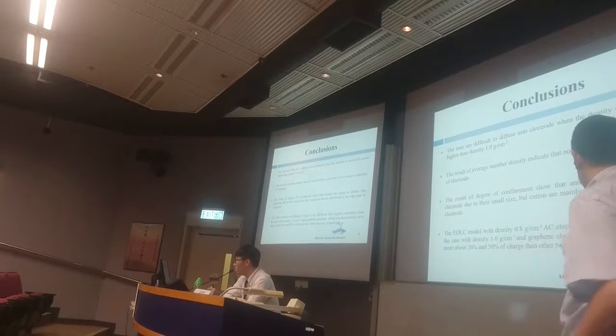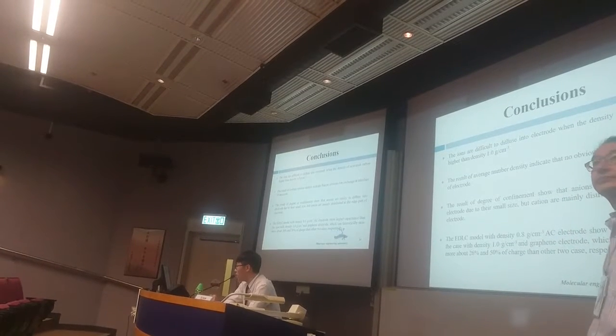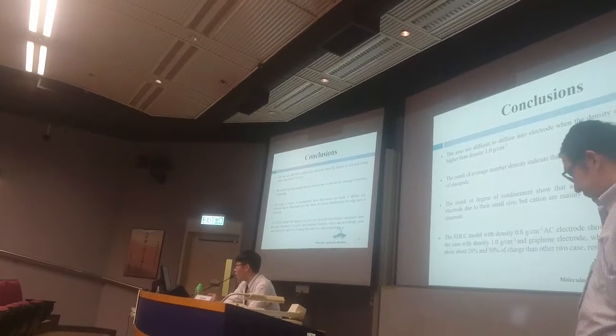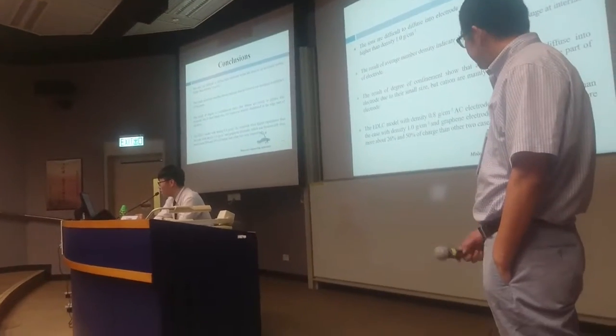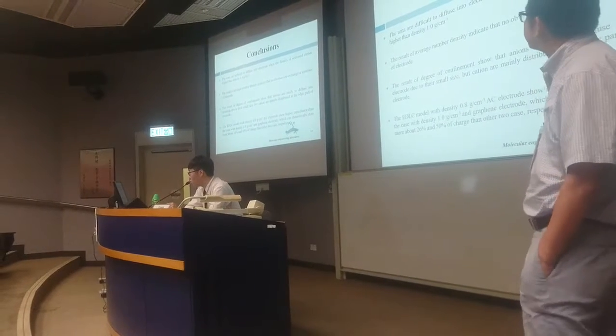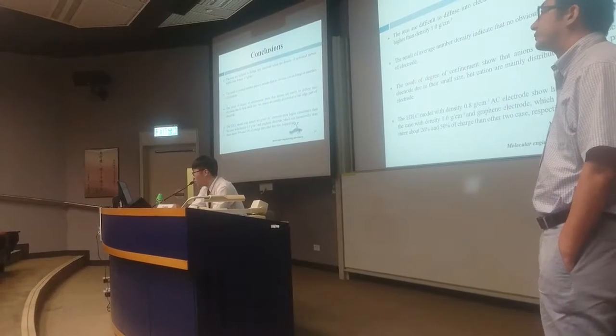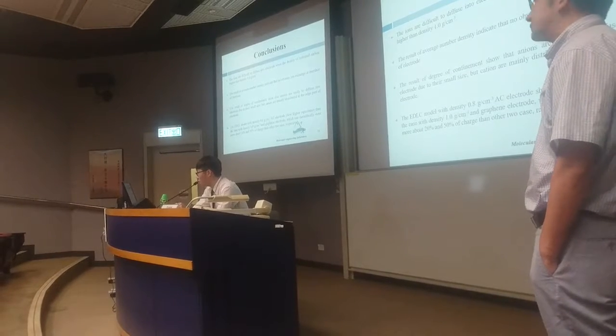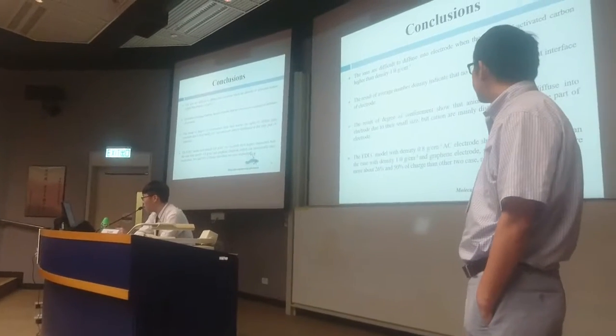The EDLC model with density 0.8 AC electrodes shows higher capacitance than the case with density 1.0 and the graphene electrode, which can theoretically store about 26% and 50% more charge than the other two cases respectively.